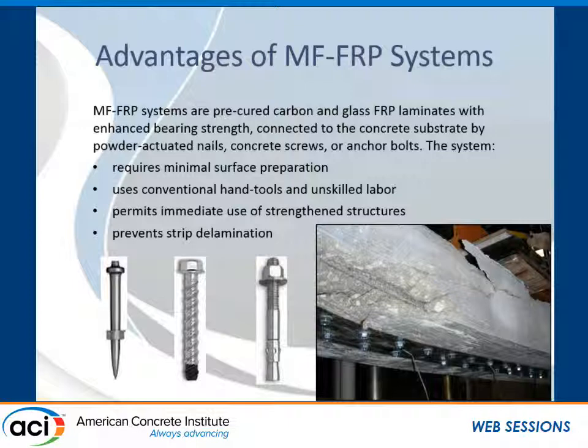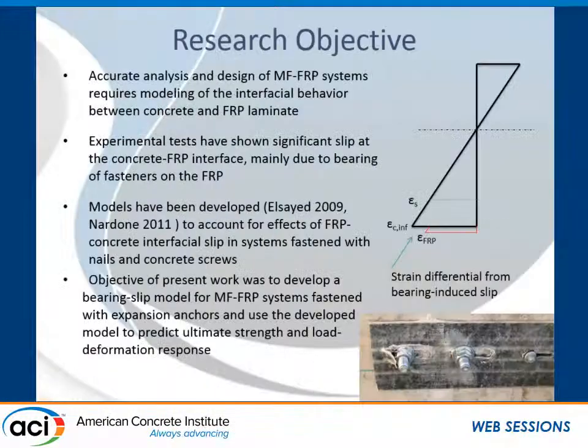Now, when they're properly designed, the MF-FRP remains firmly attached to the concrete substrate through failure, as you see in the picture here, and bearing of the fasteners on the FRP allows for a gradual failure mode, which is rather interesting. Now, the force transfer mechanism results in slippage between the concrete and the FRP at the fasteners, as you see in the bottom picture. And if we neglect the slippage effects, that's going to lead to overestimation of the strain in the FRP, because it's not the same as what I'll call the concrete interface strain at the bottom of the concrete. If we overestimate that strain, then we're going to overpredict the force in the FRP. The incompatibility between the strains affects deformations under loading and must be a consideration if we want to develop accurate models for predicting beam behavior.